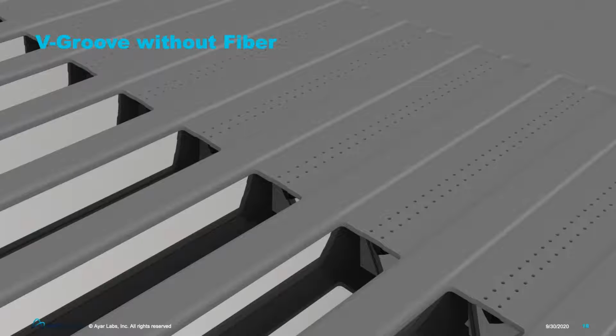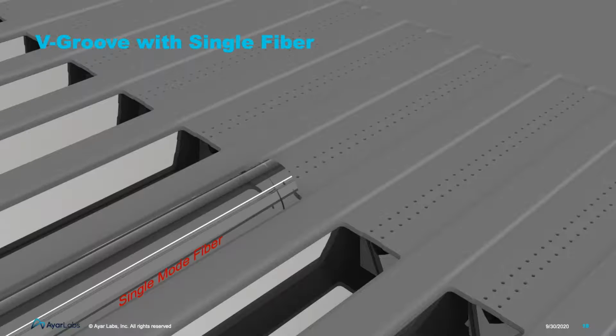Let's zoom in further to the Vgroove region. From this vantage, we note how the spot size converter bridges the undercut region. Here, I have inserted a single fiber to show how the fiber couples to the chip. In practice, all of the Vgrooves would contain one fiber, but for clarity, I have only shown one here. The optical fiber is a standard single-mode fiber, with a mode field diameter of around 8.5 microns.